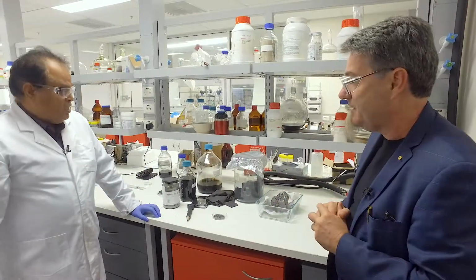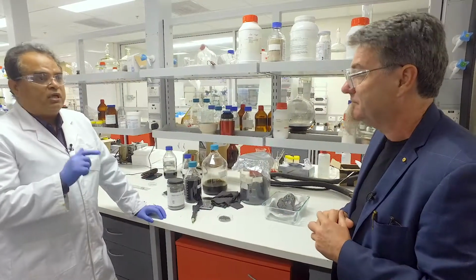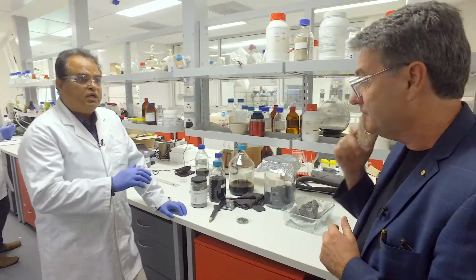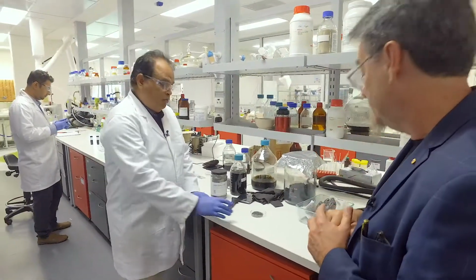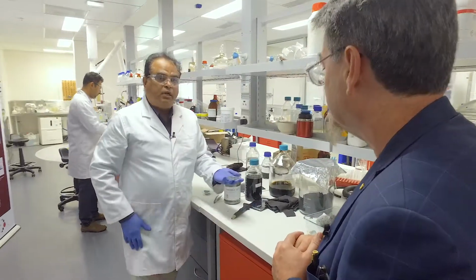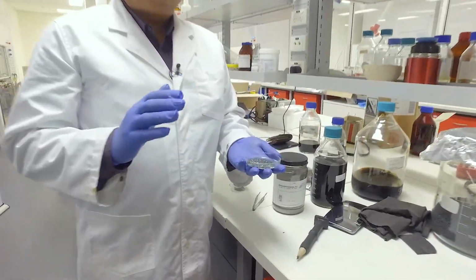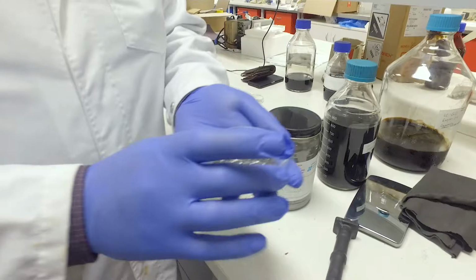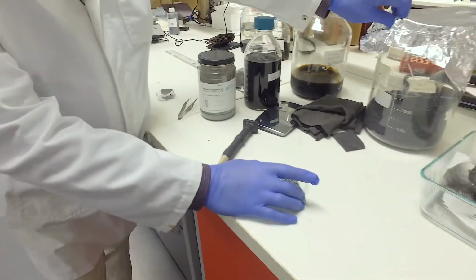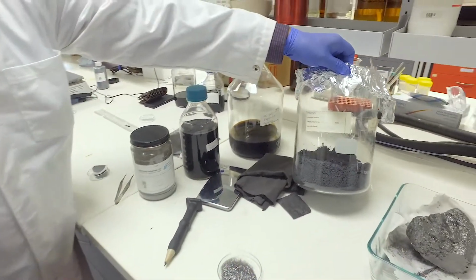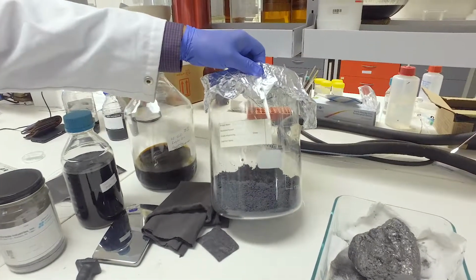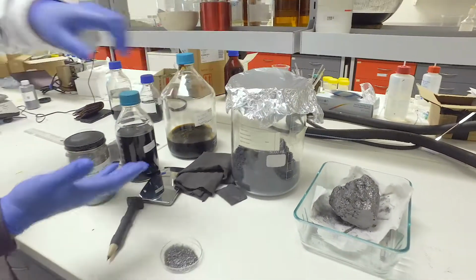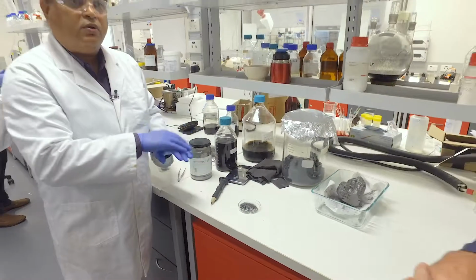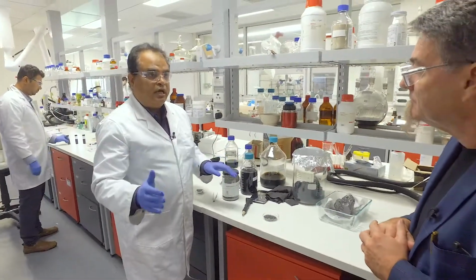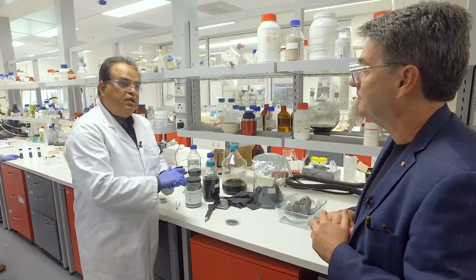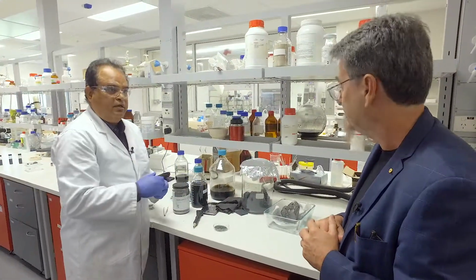The next step would be? Then we give a rapid thermal shock to this material so that it pops like popcorn. The volume expansion here, this is 2 grams of material. The volume expansion is between 700 to 900 times. So this much of material expands to this much of volume. Wow. So this is such a high expansion of this graphite. Once at this stage, now 7 to 9 sheets of graphene are stacked together. The surface area is very high. Now we can very easily chemically oxidize this material.